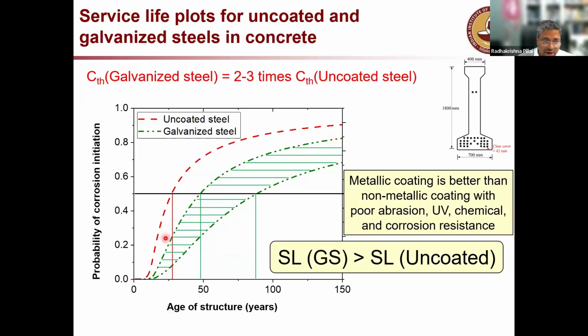So you can see here, if an uncoated steel is used, the red curve here, let's say you get about 25 years of service life. If you use galvanized steel, there is a possibility of getting a service life of from 50 to 75 years. That's very, very useful.